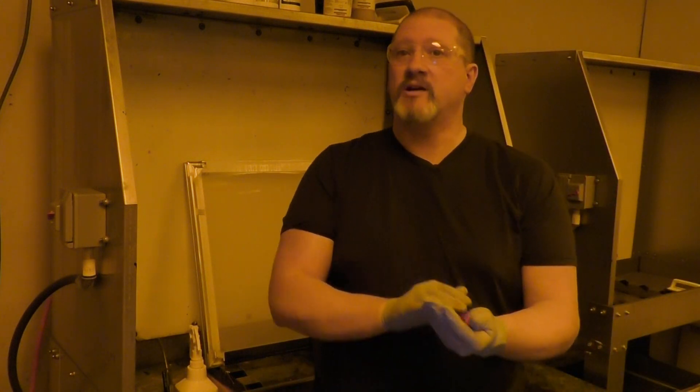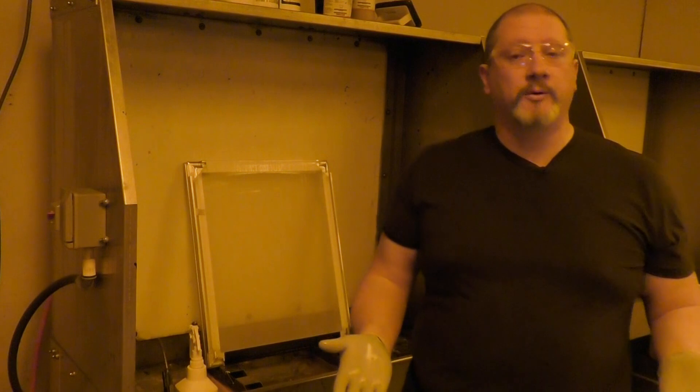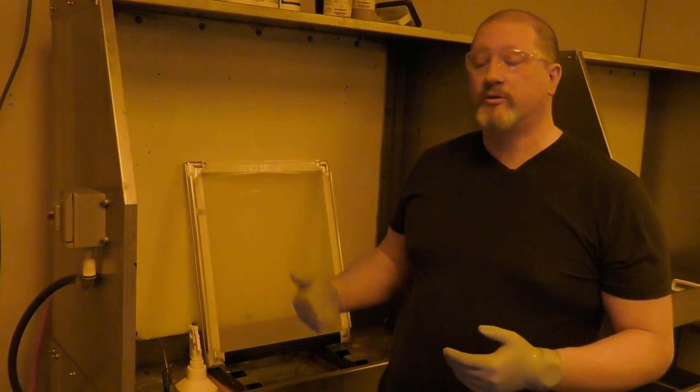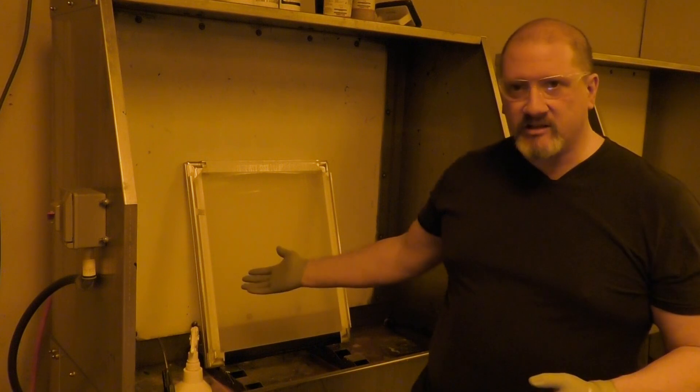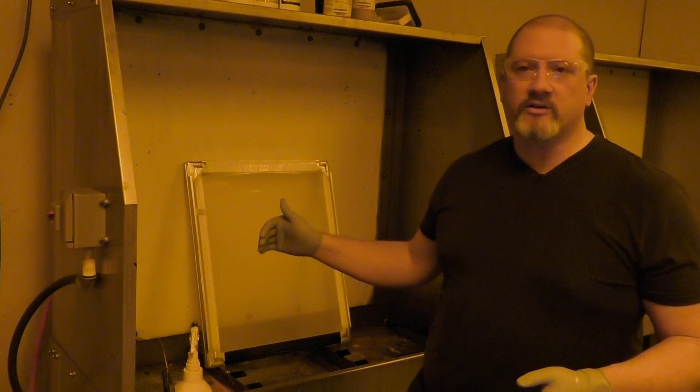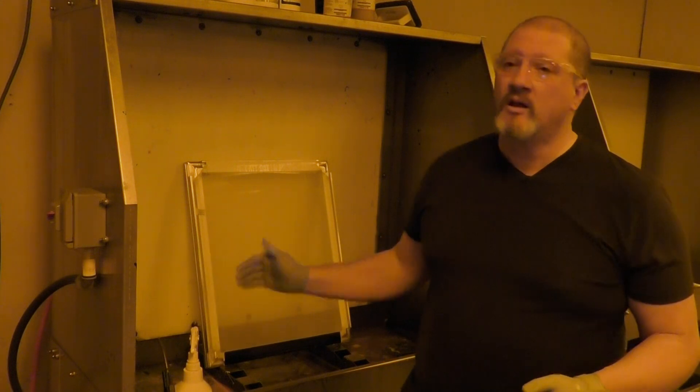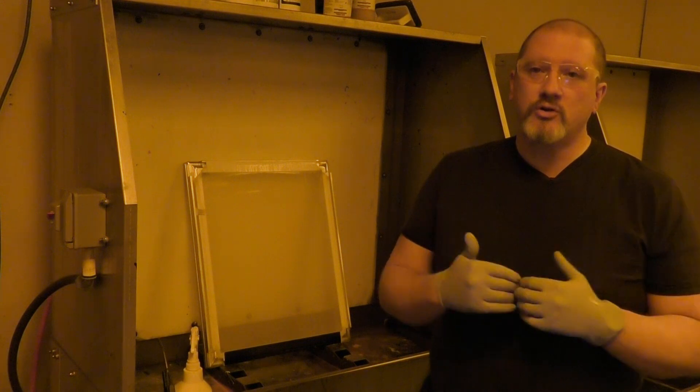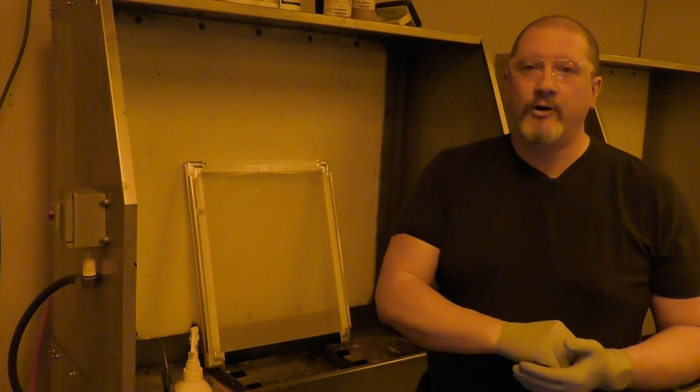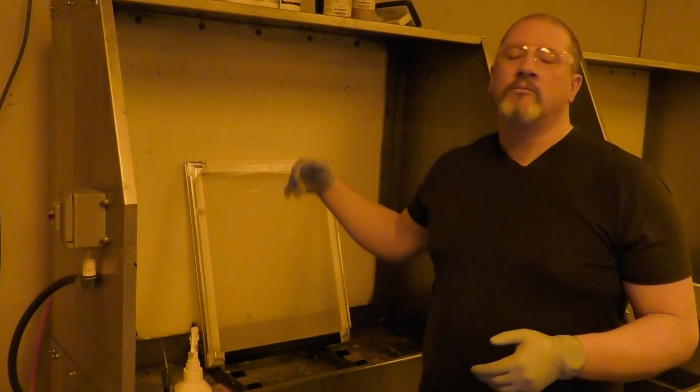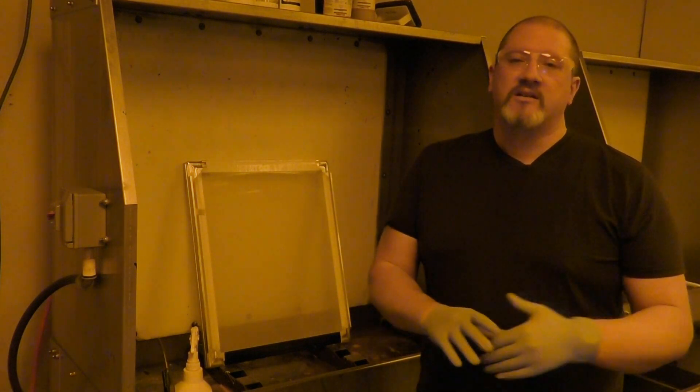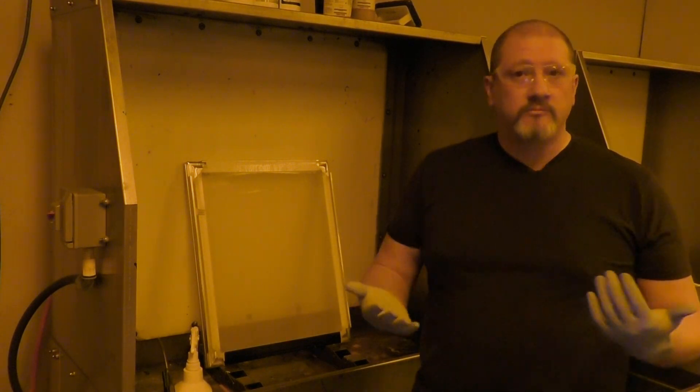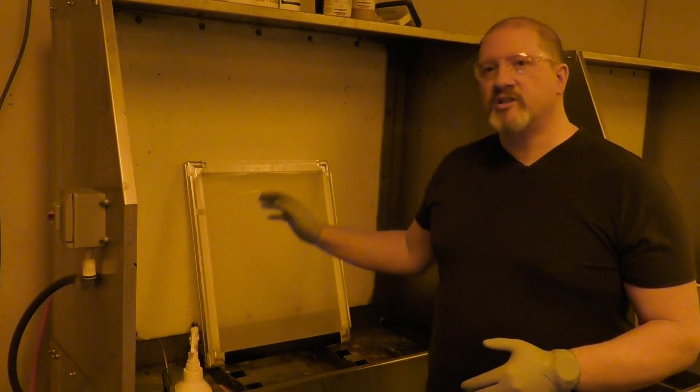Obviously we know that we can do it with the hose but it's definitely a lot more difficult. We let the stencil remover full strength sit on there, it was a good minute. I don't see the benefit of leaving it on any longer because we already knew that those areas were underexposed to begin with and because the resins were not fully cross-linked we weren't going to get any more breakdown out of it. The chemical had the chance to do everything that it could and it took a pressure washer to finalize blowing that stuff out. In the areas where you saw it stick, that's very similar to if you were to use a solvent to clean your screen. Going back to the different levels that we talked about, it's either going to take a lot or it's going to come out with a little bit of elbow grease.